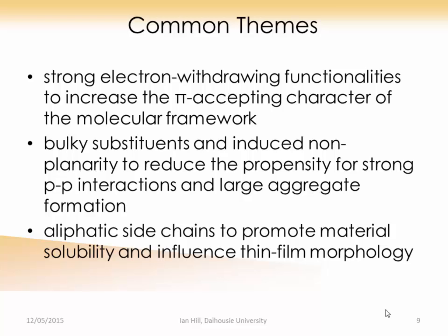And so the common themes, the takeaway messages that we have here. We always have these strong electron withdrawing functionalities to increase the accepting nature of the molecules. These bulky substituents on the molecules inhibit the propensity for aggregate formation, so we get smaller domain sizes. And these aliphatic side chains, often branched chains, promote the material solubility and also influence the morphology of the thin films.